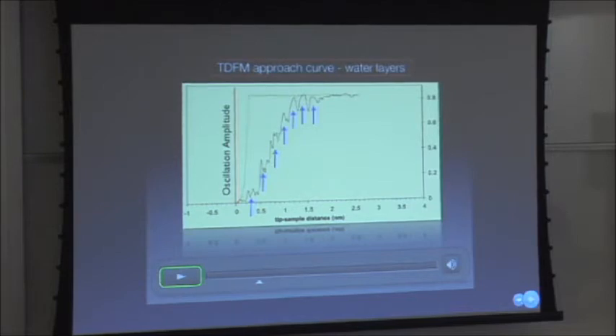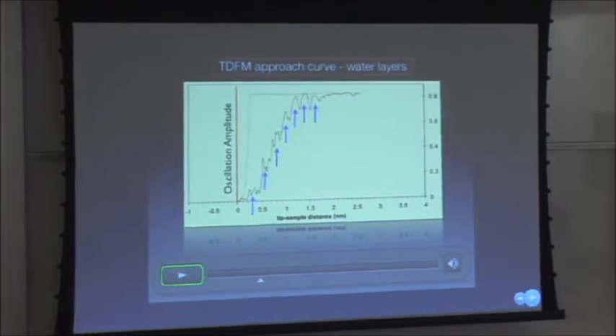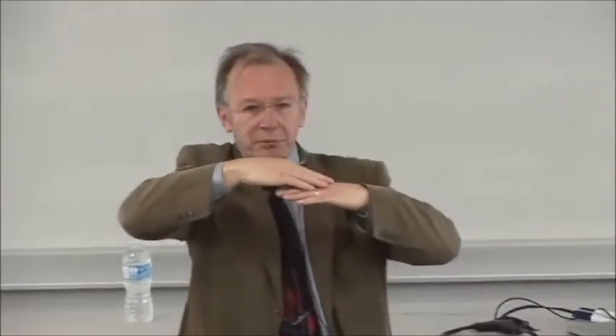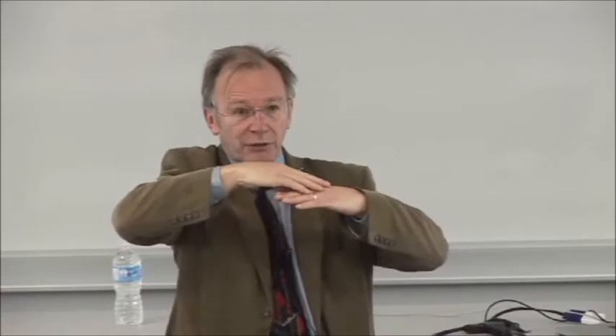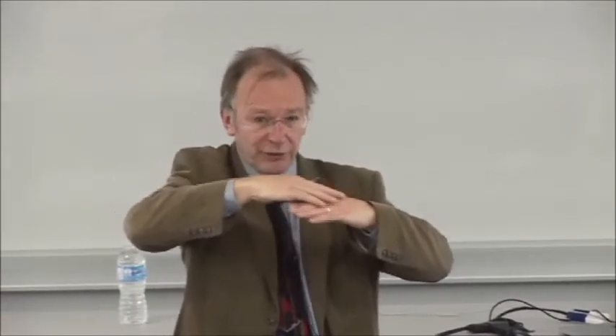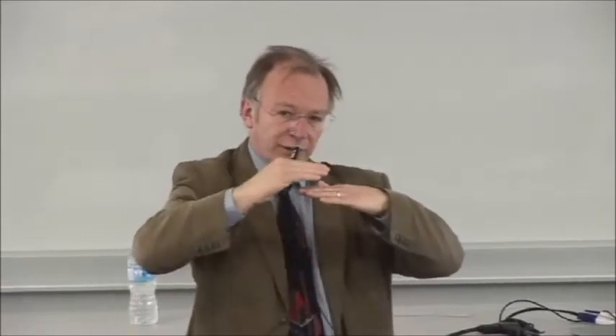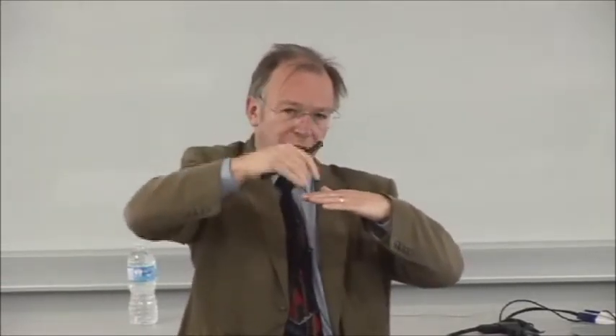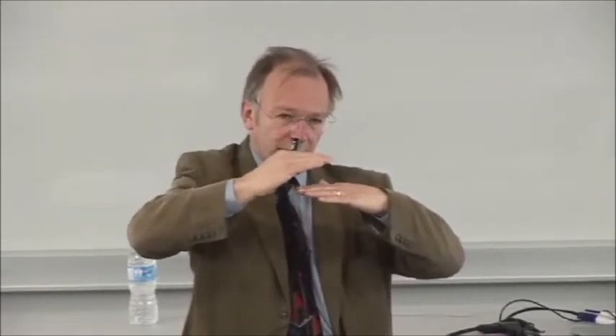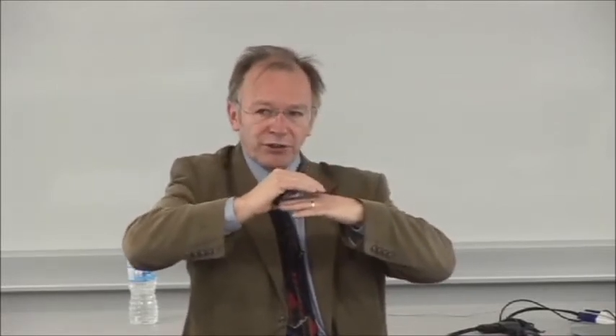So these are the water layers. We're confining the water between the end of the tip and the surface, and the water starts to order. And when it orders, it has a different mechanical property. So the viscosity goes up and the stiffness goes up. So that's what we're detecting. We're feeling the surface, not by putting a normal force on, but by just shearing a little bit and feeling how the water's mechanical properties have changed. So we know where the surface is without touching it.